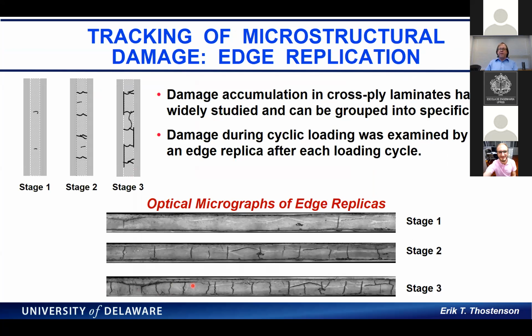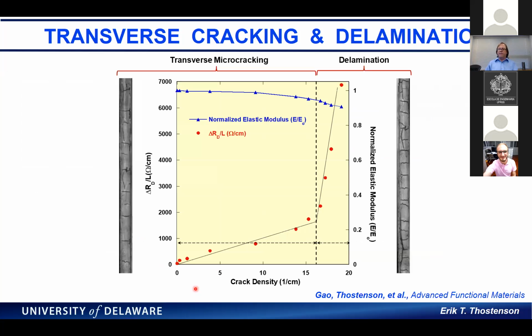These are actually optical micrographs where we took edge replicas, we polished the side of the specimen and pulled it off so that we could count the number of cracks. Very tedious work. This was done about 9 years ago. But recently, another student, this was done where the nanotubes were dispersed, but earlier this year we published another paper where we used electrophoretic deposition with similar success.